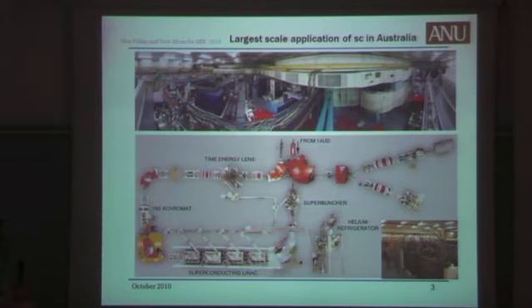Niobium on copper is also less sensitive to helium pressure variation. Actually, in a previous talk, I was surprised by the quite high pressure sensitivity. So quarter waves probably can be made really non-sensitive to pressure variations. So in spite of the high energy content in such resonators, probably you don't need a very complicated RF system.